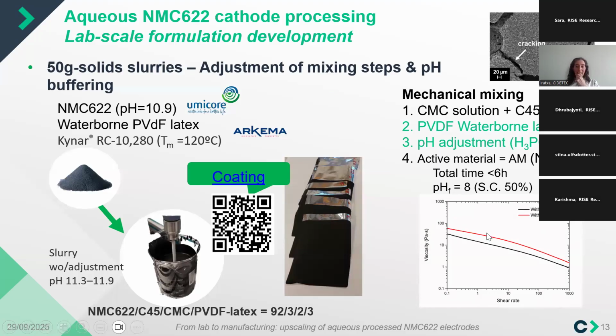Going into upscaling and manufacturing, the higher the solid content, the better, because you have lower solvent to evaporate, so less energy consumption in the drying step after the coating line. But there is always a limit—if you go too high on solid content, the slurries start to be less stable or tend to agglomerate, and you get more defects.